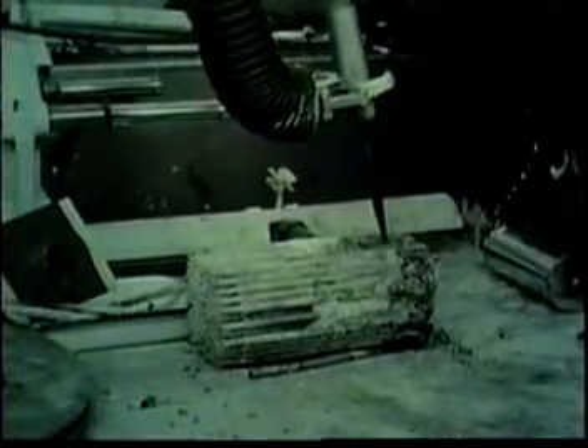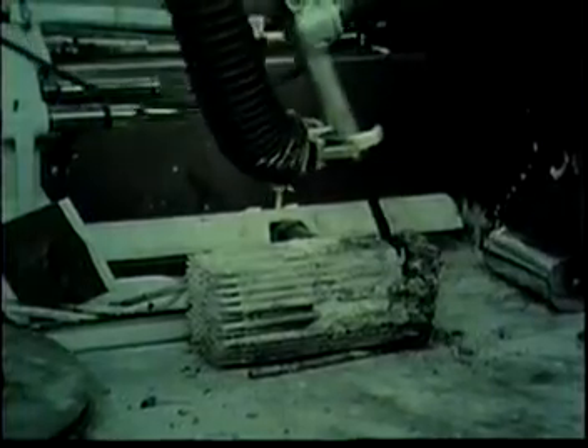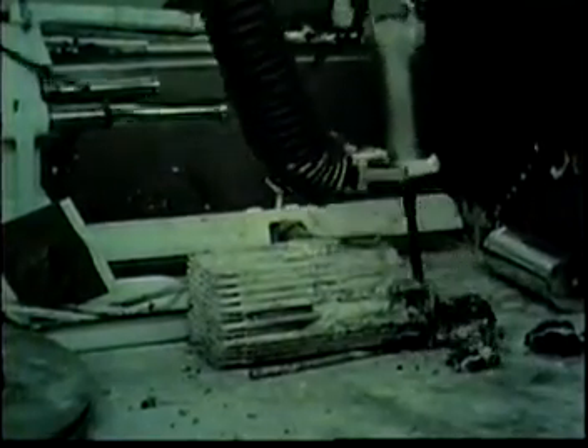The remaining core assembly was lifted by one of the special rods containing thermocouple wires. The thimble, vibrated down, loosened several large fragments of fuel material. Complete removal of the thimble exposed the remaining fuel section and lower blanket. A cut was made through the center of the fuel section. The solidified material formed in two distinct sponge-like zones of porosity was easily broken and exhibited no traces of ductility.